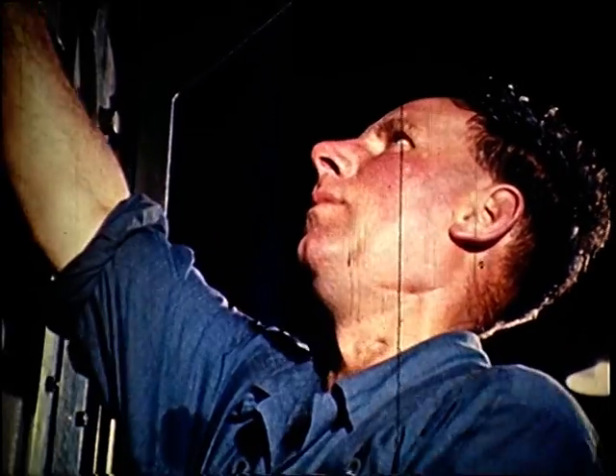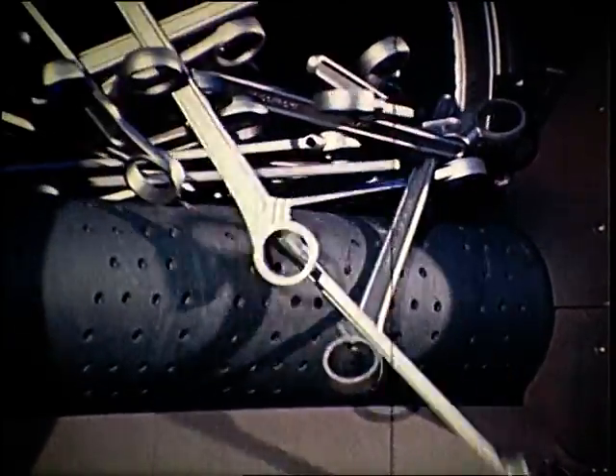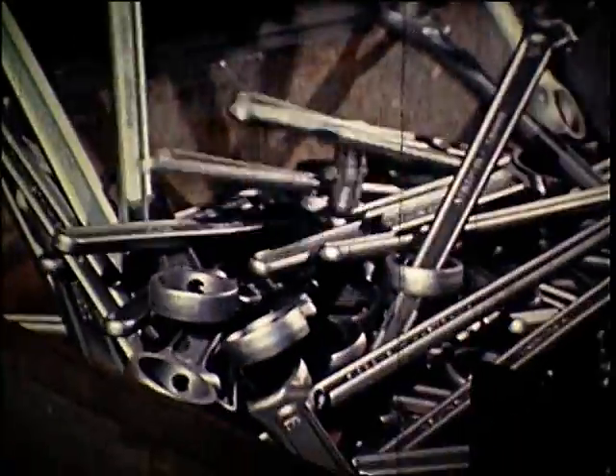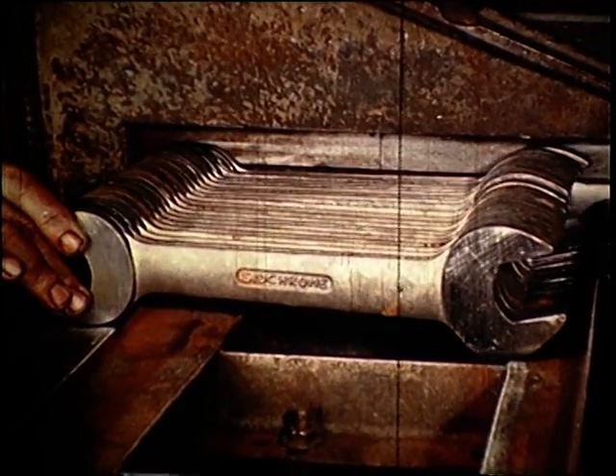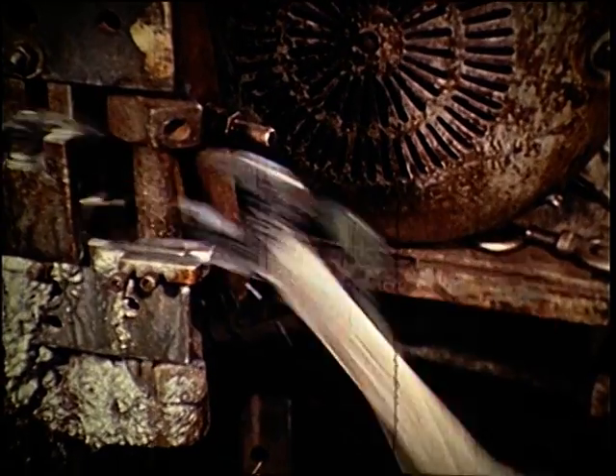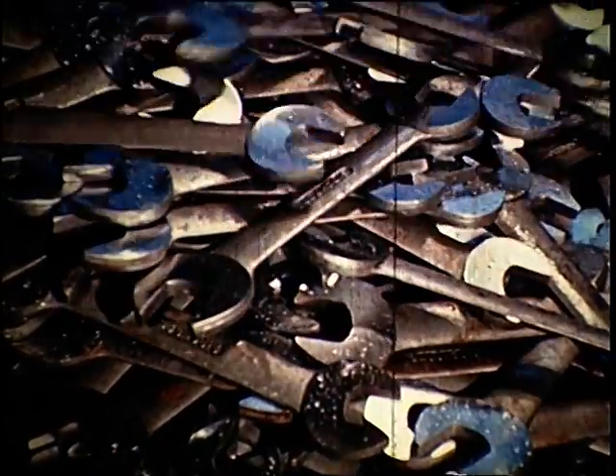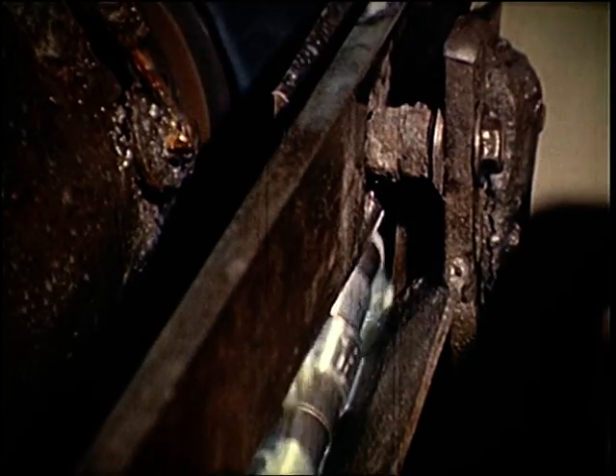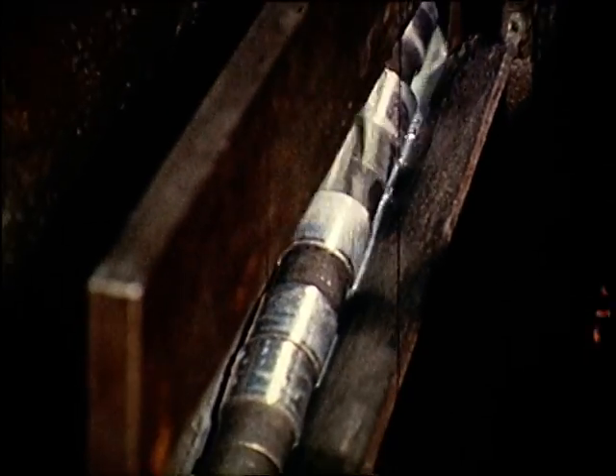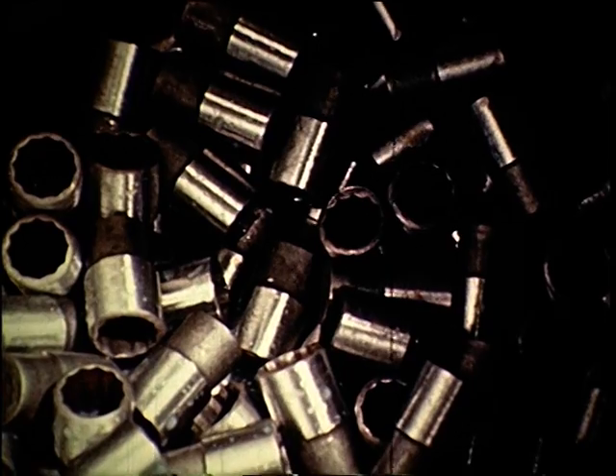After normalising, all scale is quickly removed by shot blasting, leaving the spanner with clear brands and a fine matte surface. This special purpose machine automatically grinds all four head faces to their correct thickness, with two large grinding wheels producing flat and absolutely parallel faces. Sidchrome sockets are fully forged to ensure that the grain flow follows the contour of its shape. Sockets made by punching the serrations from a drilled bar have the grain flow cut, thus weakening the material. Here, centreless grinding produces correct wall thickness and fine finish.